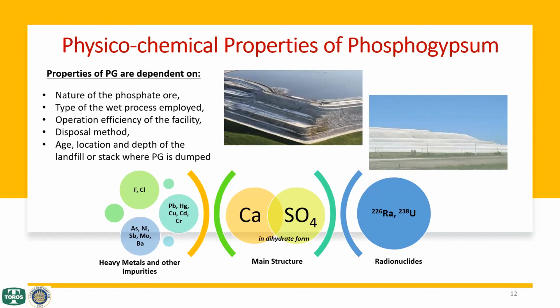PG is also known to contain trace elements such as arsenic, silver, barium, cadmium, chromium, mercury, lead, some rare earth elements, and radionuclides. All of these impurities vary in a wide range depending on the phosphate rock used in the process, but the type of wet process, operational efficiency, age, location, or depth of the landfill also plays an important role in the properties of phosphogypsum.